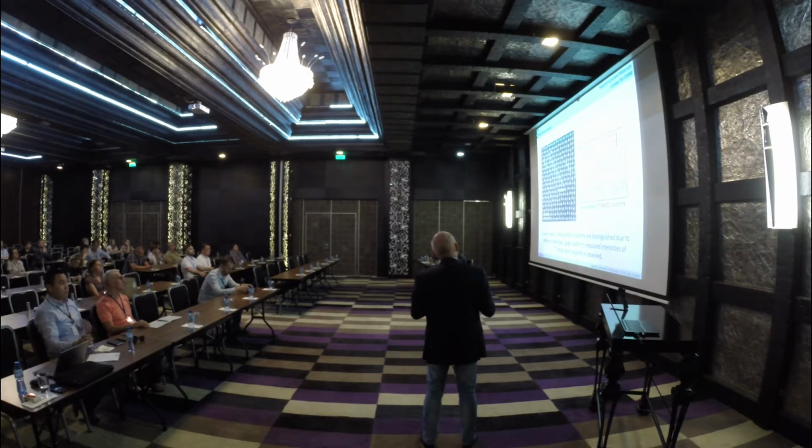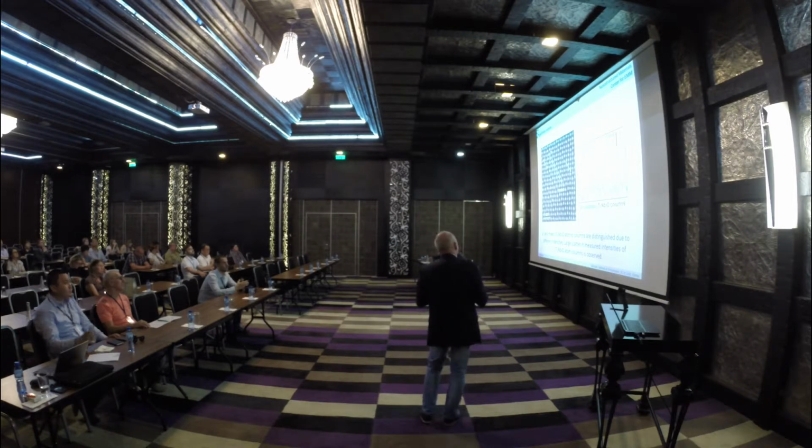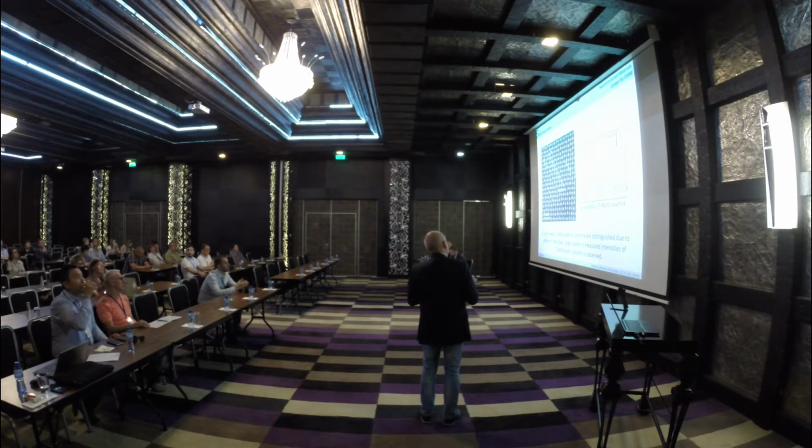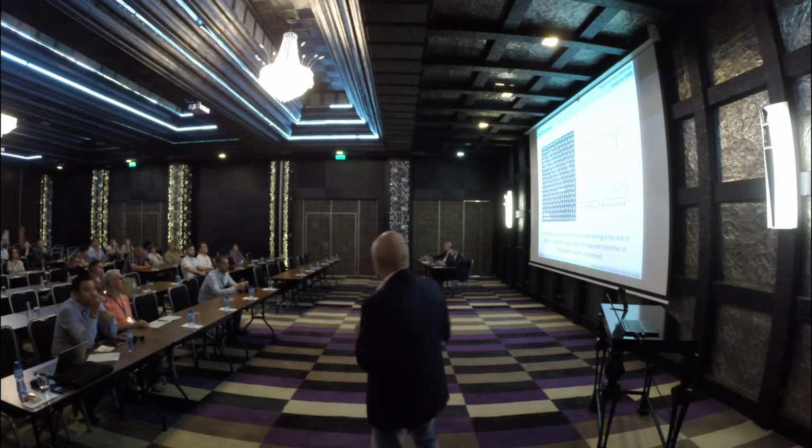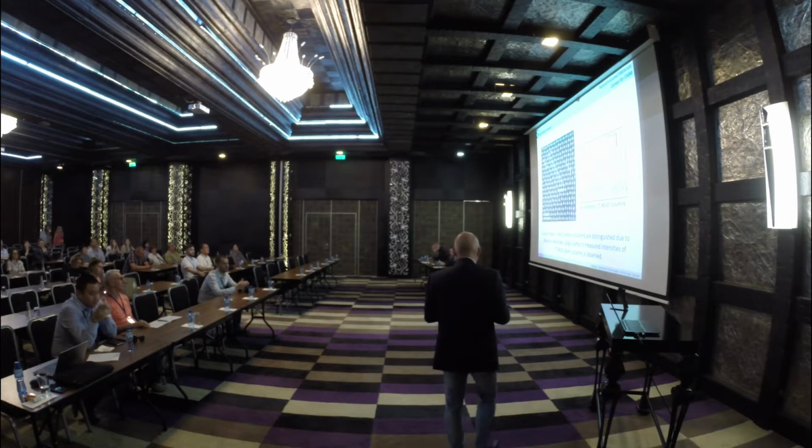This is the mixed titanium and niobium on the B site, and these are the strontiums. If you take the experimental profile across those titanium mixed columns, which are the red ones here, we see that there is a lot of scatter. That means that the concentration of titanium and niobium on the B site is not very evenly distributed within the single atom columns.